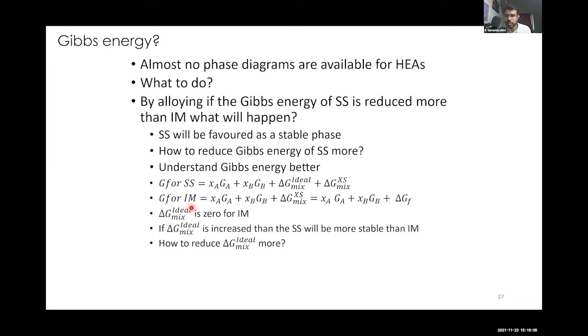Gibbs energy for intermetallic phase has this kind of expression. Here this delta G mix ideal is there for the solid solution, which is one extra term which is missing in the case of intermetallic phase. So what is this delta G mix?